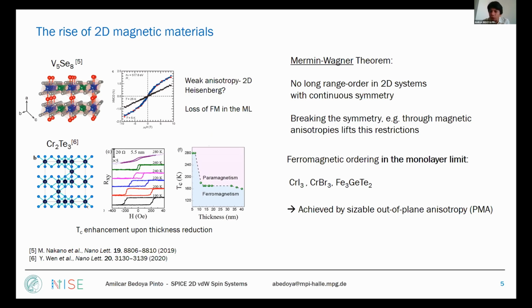There's another interesting recent example. This is chromium-2 tellurium-3, where they have a very peculiar observation: when you reduce the thickness, they don't get to the monolayer regime, but they reduce the thickness to less than 10 nanometers, and the TC increases dramatically. So that's actually another, although this is not a true 2D regime, that might give us some hints of other types of interactions that are important in this regard.